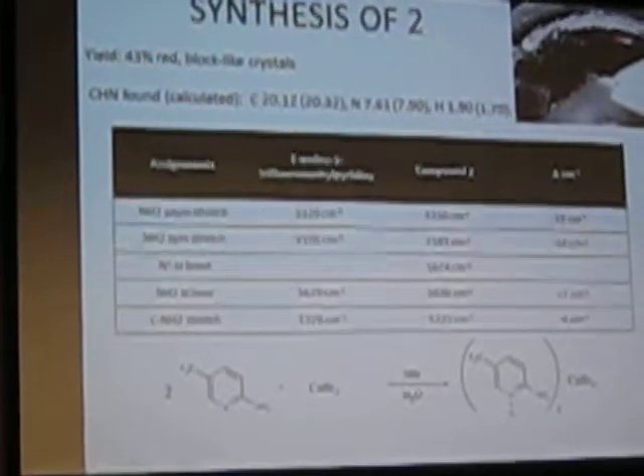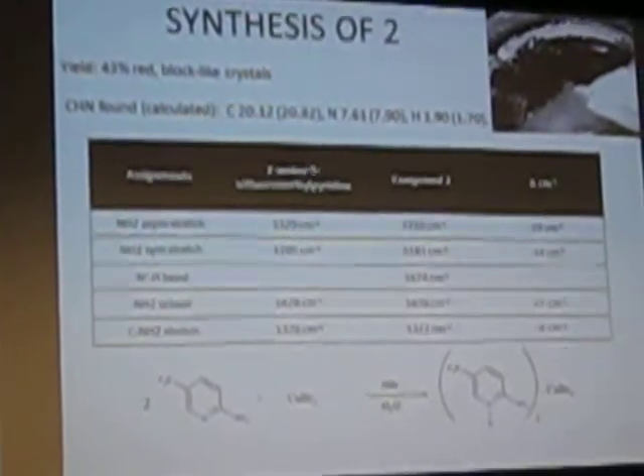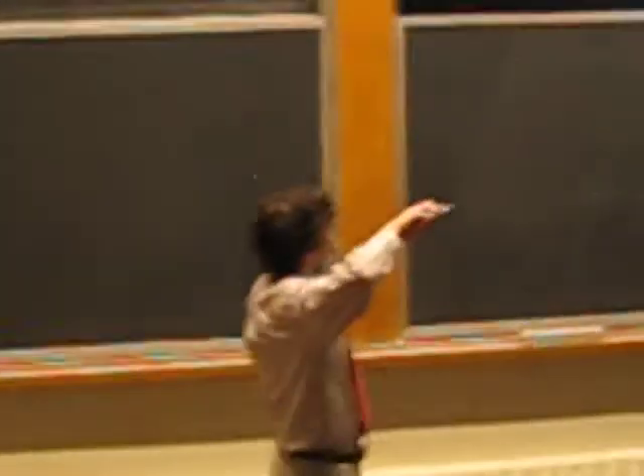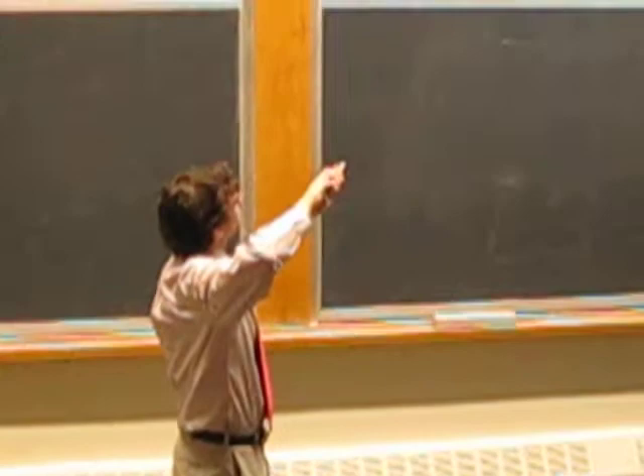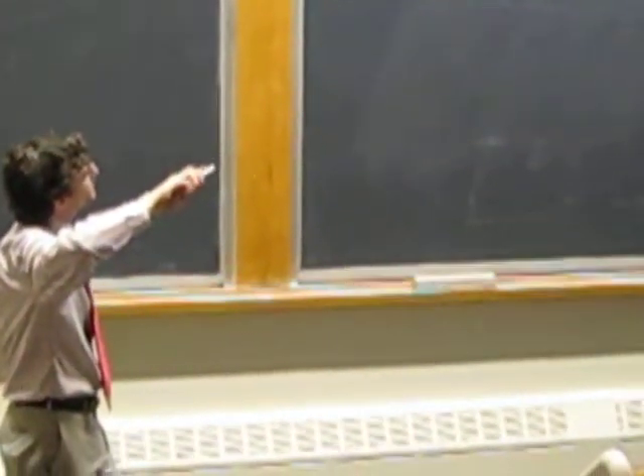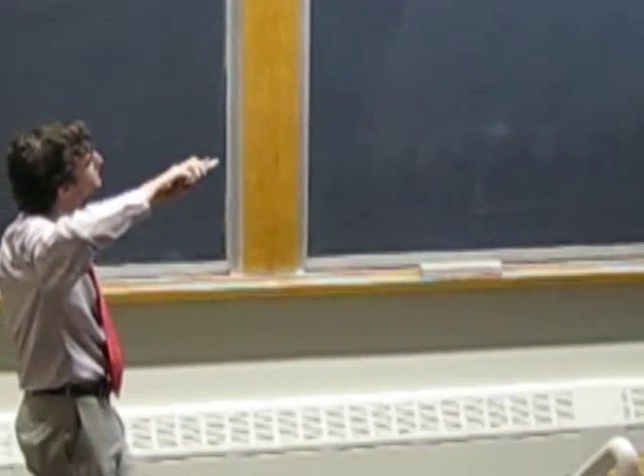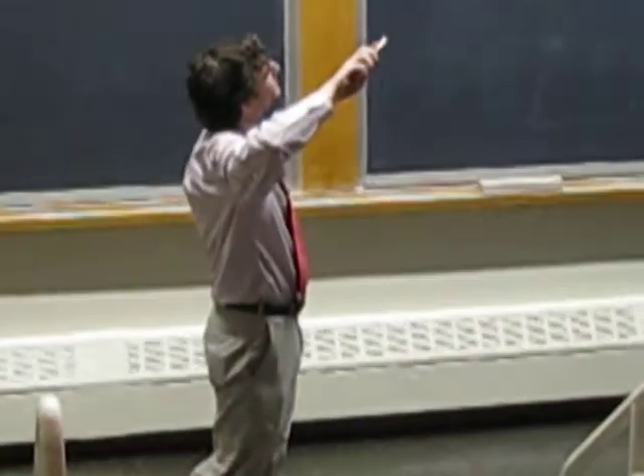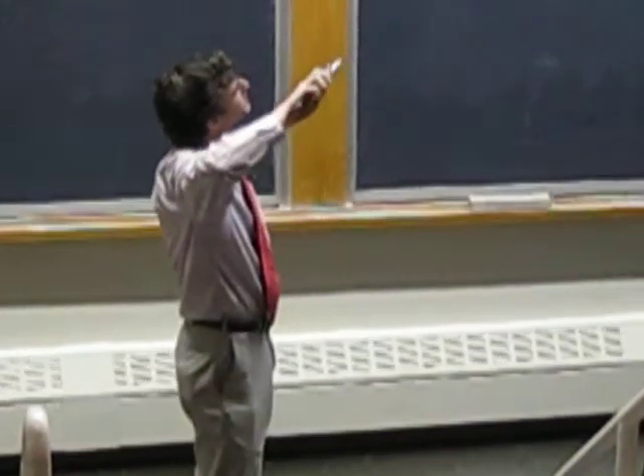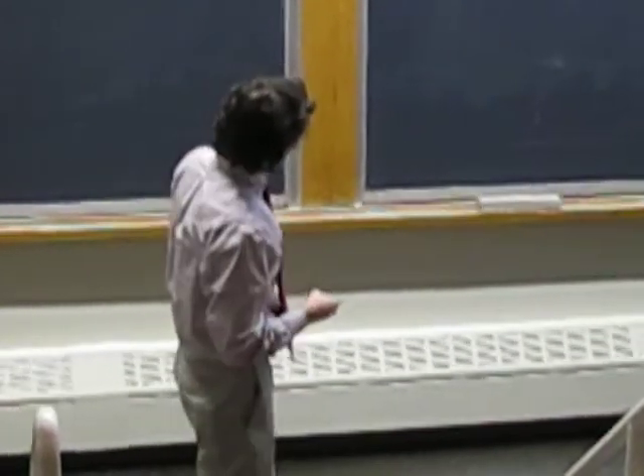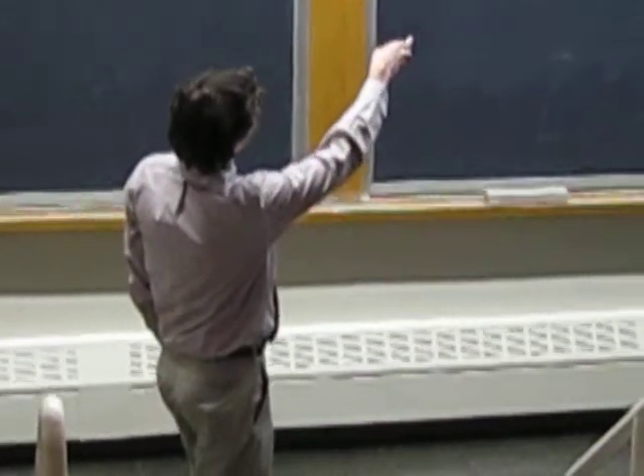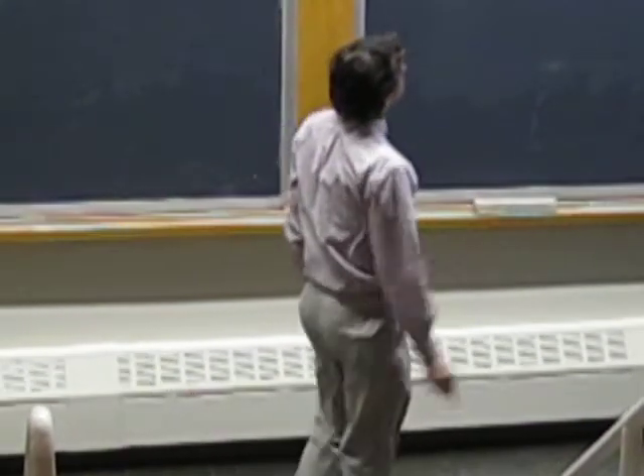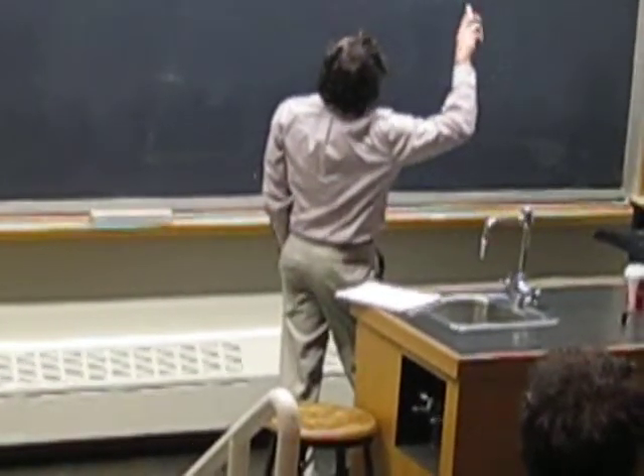Okay, so then I'm moving on to the tetrabromo cuprate synthesis. So again, the synthesis is rather straightforward. It's about the same scheme as before, just reacting the two components in a 2-to-1 ratio in an aqueous solution with a little bit of acid, slow evaporation over a couple of weeks will give you the crystals, red block-like crystals. And again, we can see the protonation of the pyridinium ring was successful, and the composition agrees with the final product.